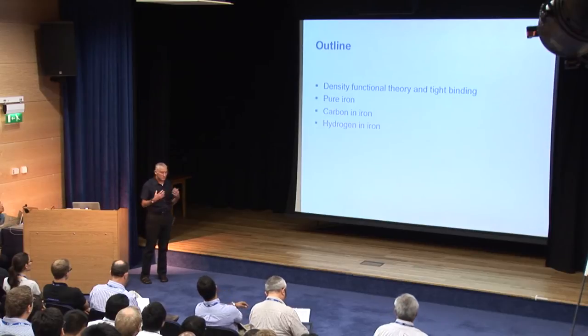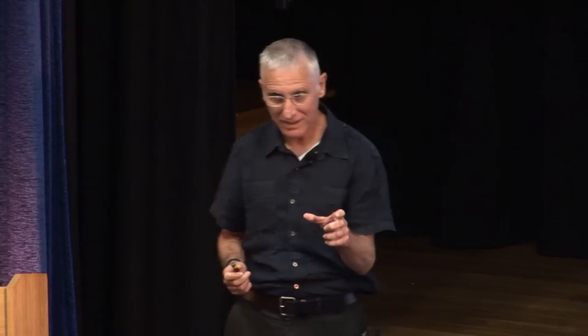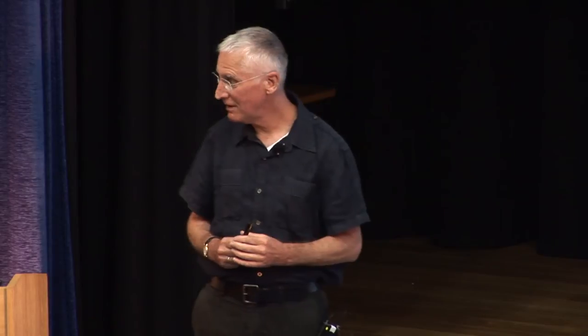The challenge for me with carbon in iron was creating models and understanding phenomena that are very well known: the carbon is associated with the octahedral site in the dilute limit of BCC iron, but in the concentrated limit, if you were to make a fictitious Fe4C phase in the BCC structure, then the carbon would be in the tetrahedral sites. At some concentration, the system goes over to preferring the octahedral sites with the associated tetragonal distortion one encounters in martensite. The carbon acts something rather like what physicists call a polaron, in which there is a dipolar force which reorients through 90 degrees as the carbon diffuses.